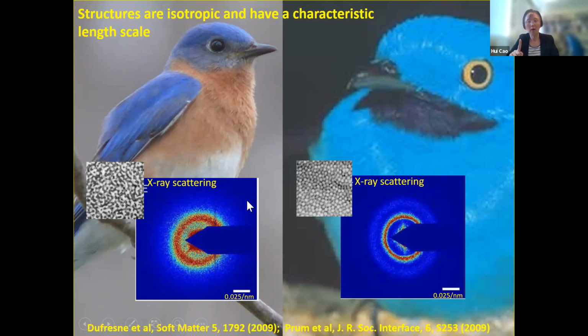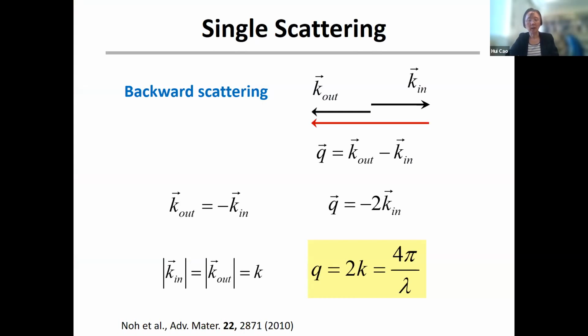So this ring tells us there is a dominant spatial frequency in this structure. That dominant spatial frequency corresponds to the radius of this ring. And because this dominant spatial frequency is the same at all angles, the structure is isotropic. So that's why they produce this isotropic color. But this color still comes from the underlying order in this structure that leads to the interference effect. So now let's see how the dominant spatial frequency will determine the color of reflection. Let's consider light coming in with a wave vector k in. Then it will be scattered by the structure once, and then it's going back. So in the backward direction, we have another wave vector, k out.